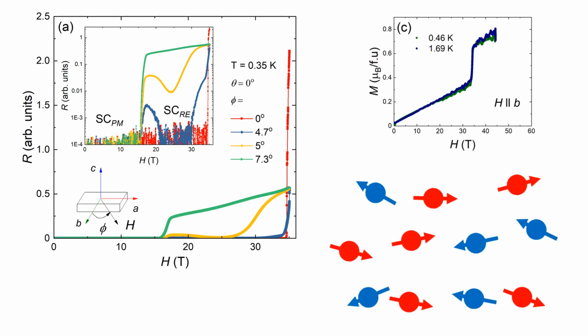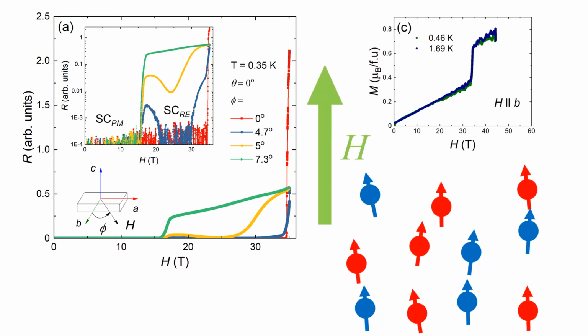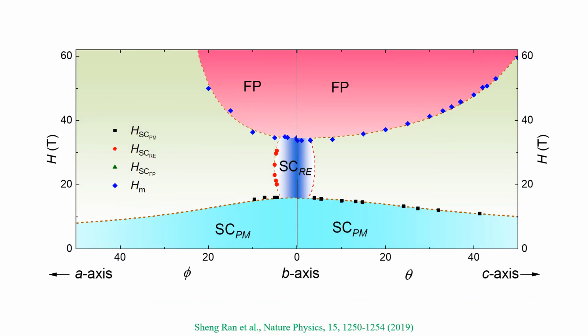In the low magnetic field, the magnetic easy axis is the a-axis, but there is no magnetic order. The spins are roughly along the a-axis, but not ordered. When the magnetic field is applied along the b-axis and reaches 35 Tesla, all of a sudden, all the spins rotate towards the b-axis. It is like a ferromagnetic phase, but induced by magnetic field. So we call this a field polarized state. Here's the entire angle phase diagram. Here's a superconducting phase, re-entrant superconducting phase, and here's a field polarized state.